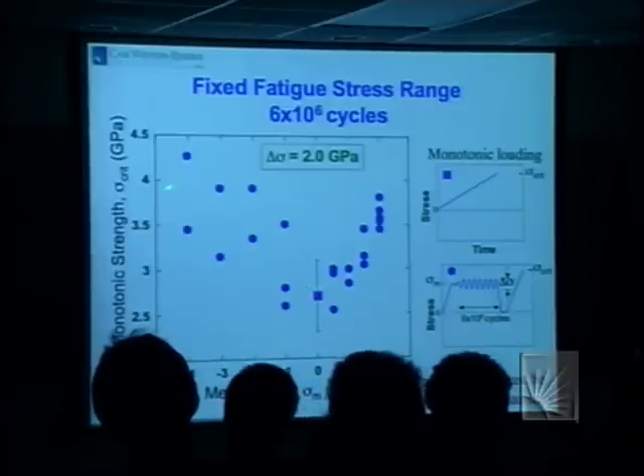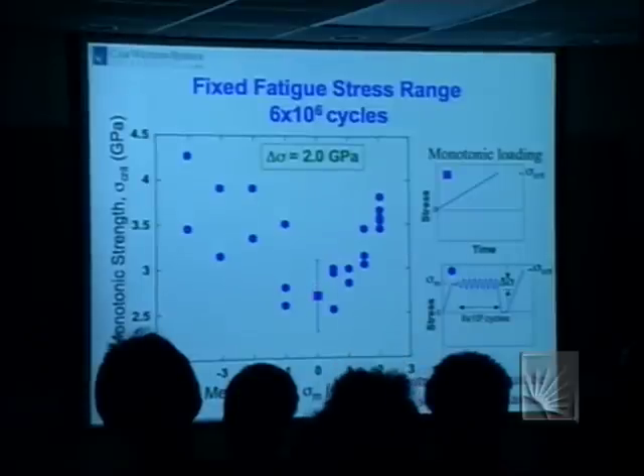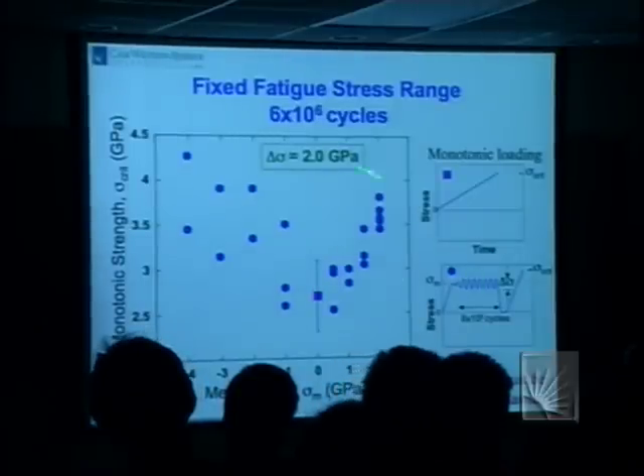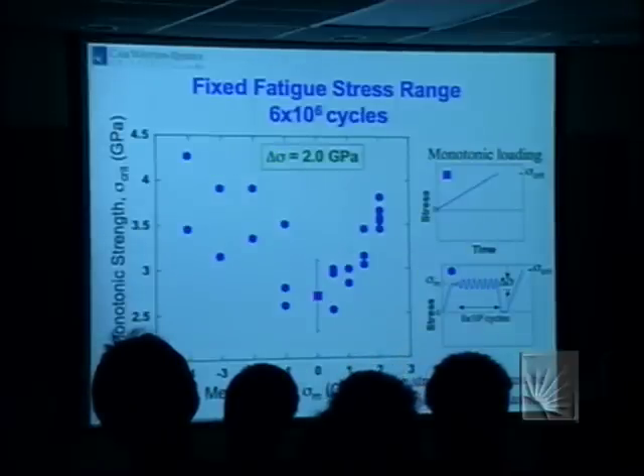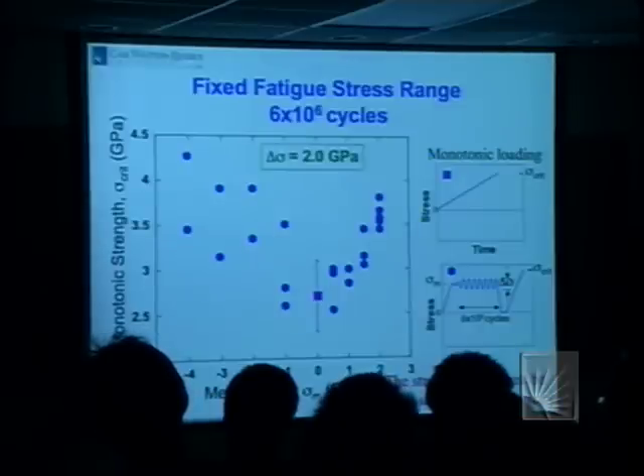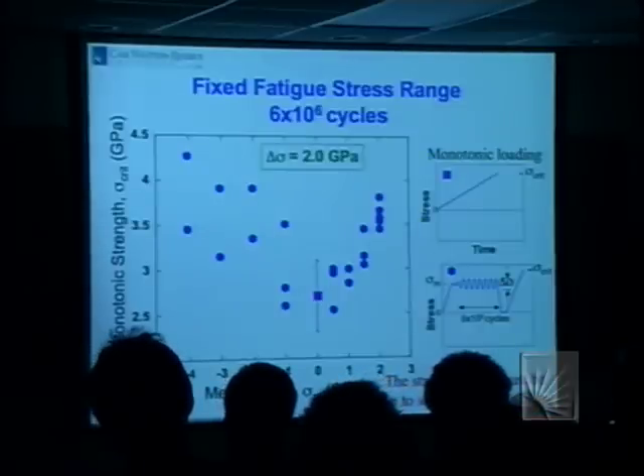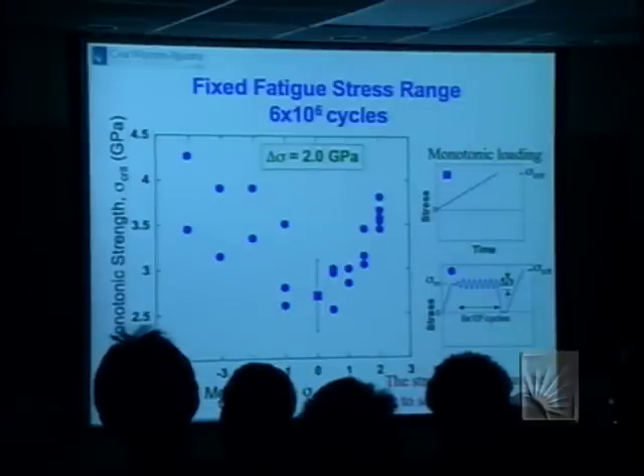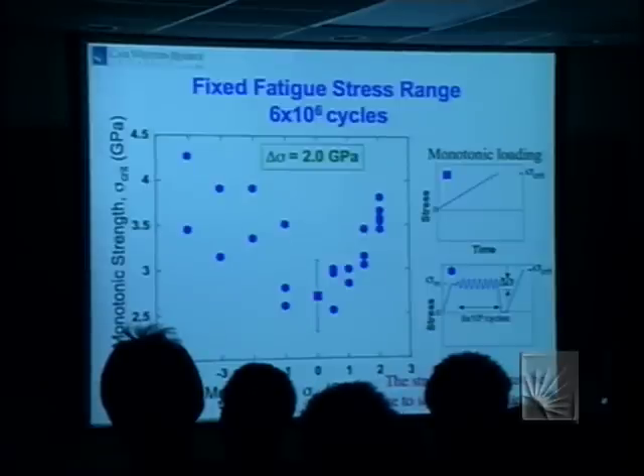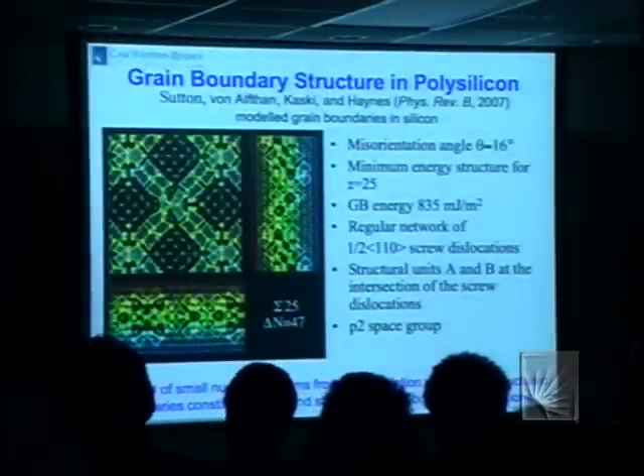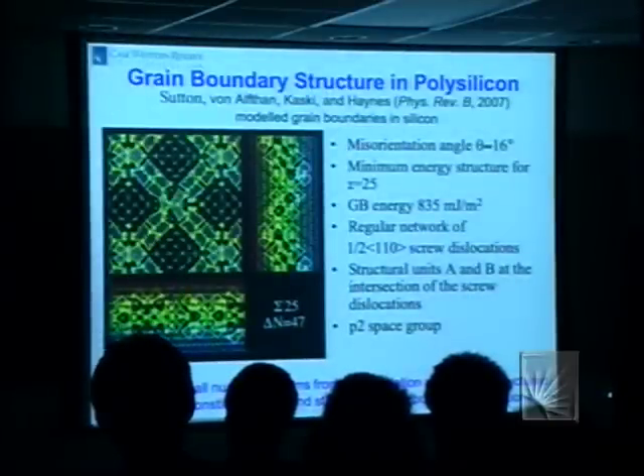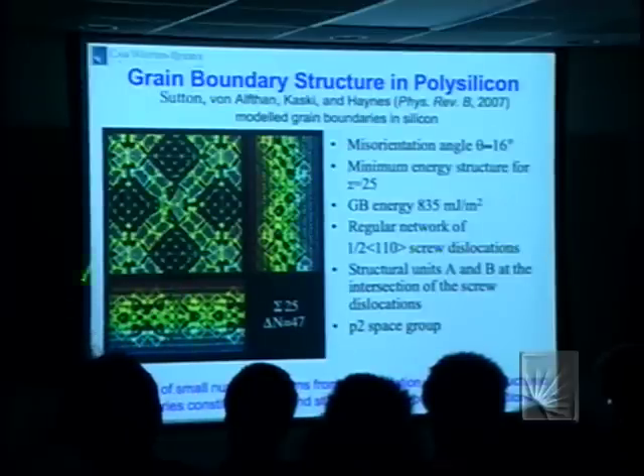But at large compressive mean stresses or large tensile mean stresses, and by the way, we fixed this delta sigma at 2 GPa, at large values of the mean stress, we got strengthening. There must be some form of plasticity. And we know that there's almost no example of plasticity in silicon until you get to temperatures of about 600, 700, 800 degrees. The next two slides are speculative, but there have been some recent calculations by a very well-known theorist, Adrian Sutton, who showed, and the details of his calculations aren't important, who showed that when you make silicon